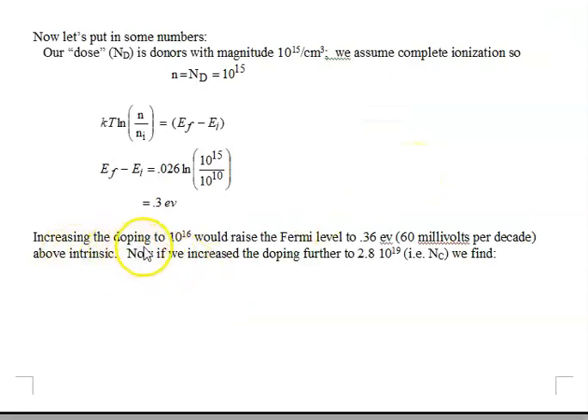Now, if we increase the number of doping atoms, increase the doping dose to 10 to the 16th, we would find that the Fermi level is now raised up further. As we increase the doping, the Fermi level moves up from 0.3 to 0.36, which is to say 60 millivolts, and that's a very important number. Every time we change the doping by a factor of 10, the Fermi level moves by 60 millivolts, which is why we say 60 millivolts per decade.